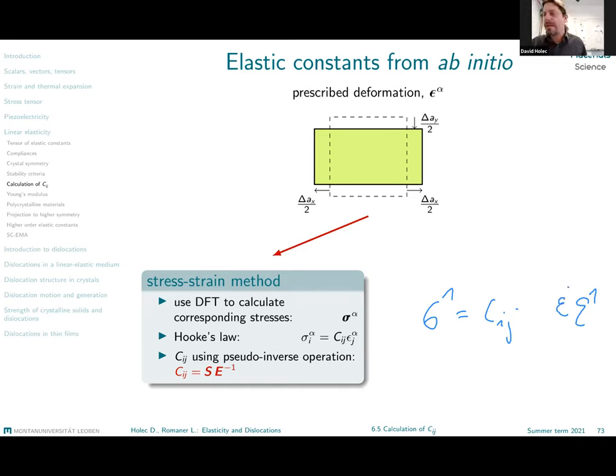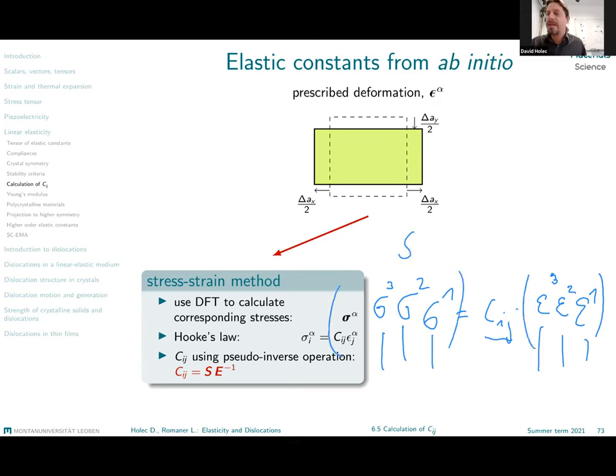I can do the second type of deformation and have the second column of the stresses. I apply a third type of deformation and get the third type of stresses. Now those are individual columns, right? Column vectors, all of them related with the same matrix of elastic constant. So when I arrange now those as really columns of matrices, label this as S and this as E, then the matrix of elastic constants can be calculated as S times the inverse E. This is so-called stress strain method.